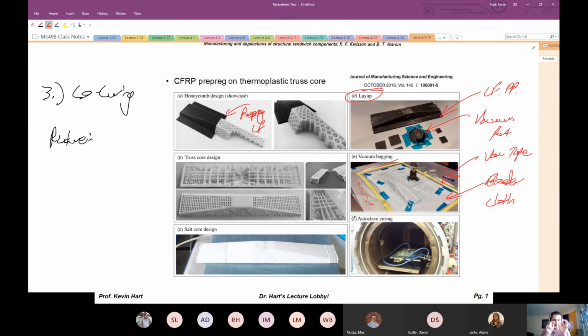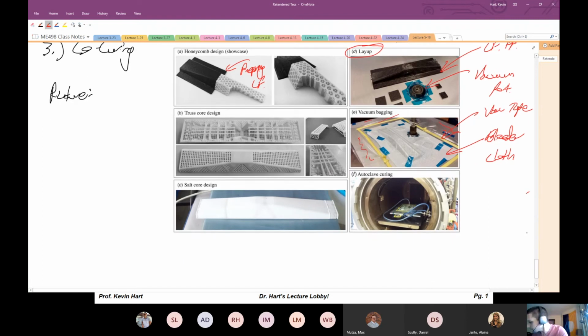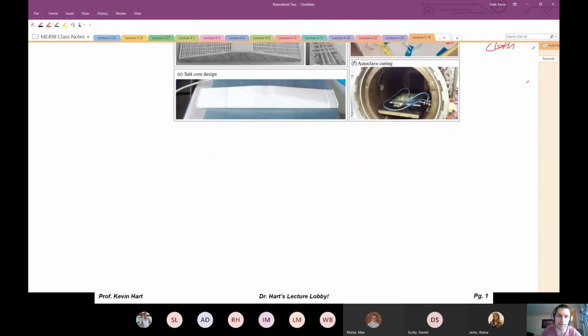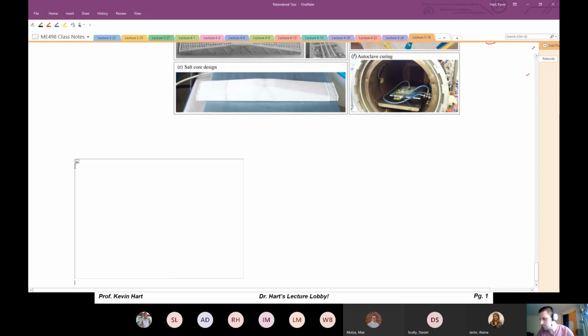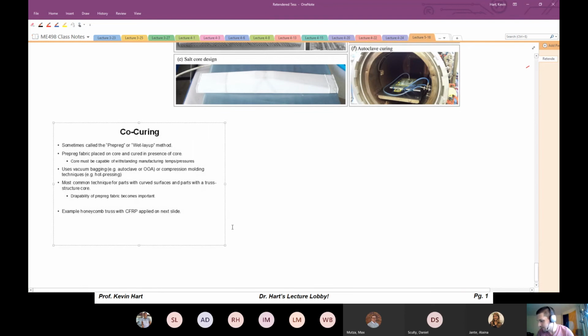And so you've got this face sheet that is prepreg carbon fiber that will be cured in the autoclave alongside the core that is the truss structure. All right, so this is an example of co-curing because you're curing the carbon fiber directly onto the core itself. That's a co-curing of a sandwich structure. So in this particular situation, here's your co-curing information.